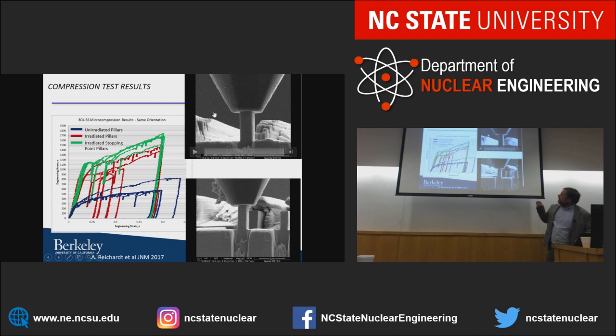And so here's my indenter. This is unirradiated. This is irradiated material. And we record a stress strain curve as you do that deformation. There's nothing too exciting in the unirradiated material. It just deforms and just flows. In the irradiated one, I want you to pay attention. There's going to be a white line popping up here and another white line popping out somewhere here, which can be associated with these very distinct large load drops within the stress strain curve.